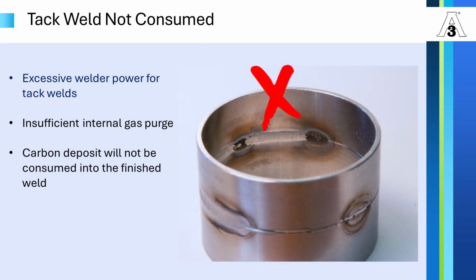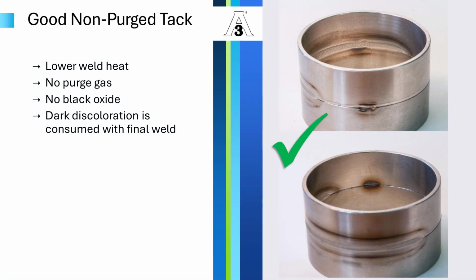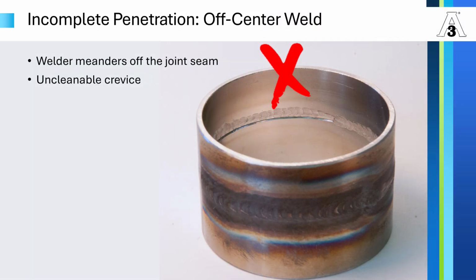You don't fix it. We talked about this earlier, the tack welds. Tack was too hot, penetrated the line, causes sugaring, and the welds never can consume that properly. Good tack weld. We addressed this yesterday as well, the lack of penetration. We talked about the sulfur content causing lack of penetration at times, the weld bead wanting to move off. This can happen as well.